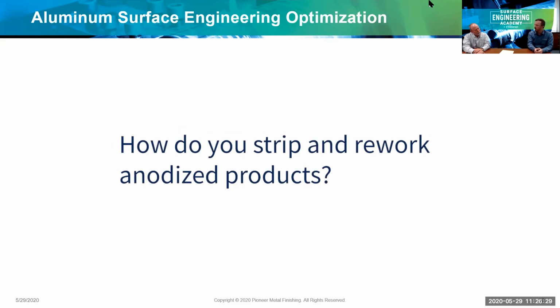Correct. Excellent. Really kind of sets us up for the next question, and that is, what about reworking or repairing anodize? Strip and rework, really a delicate subject in terms of having to remove the initial coating and remove the material. Right. So this kind of just leads from the last question of, if I put 2 mil of hard anodizing on a part, I've got half of it penetrated into the base metal. Anodizing is a non-conductive coating. That's one of the challenges. We're using electricity to form the coating, but as we make the coating, it's making the part non-conductive.